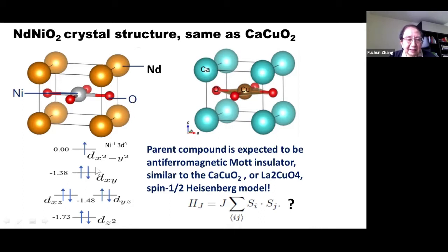The simple electronic structure tells us that this nickel here is 1 plus, so the x squared minus y squared orbital of the nickel 3d will be left. This is, I think, the most relevant part. If so, then we will have a Heisenberg model very similar to the cuprate. In passing, I will just inform you that the J here is much smaller than in the cuprate, because the atomic energy level difference between the d orbital and the oxygen 2p is much larger in nickelate.